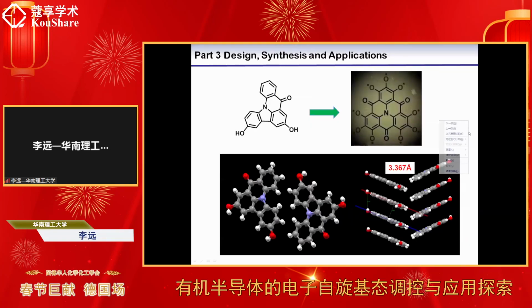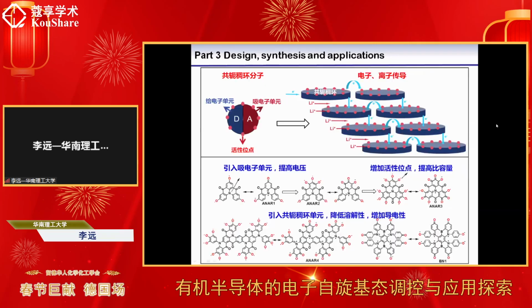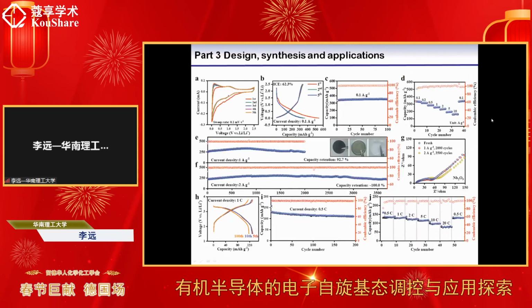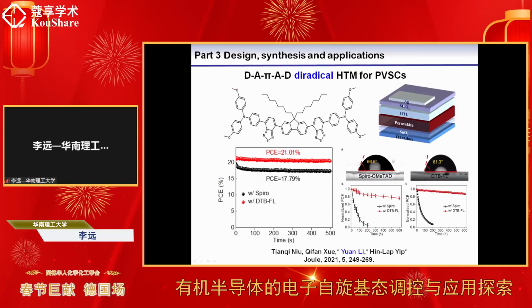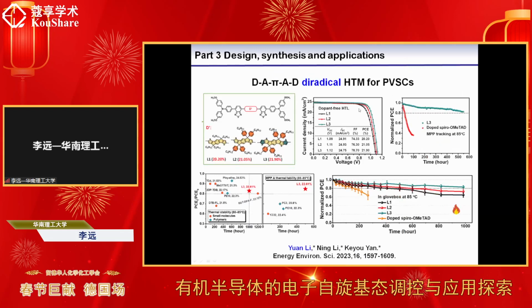And these are our results, which have not been published. We showed that the polymers based on radicals showed very good performance as the cathode of lithium batteries. It's very stable and has very high capacity. Also, we show some application of the diradical in perovskite solar cells, for this kind of DA-pi-AD diradical. It has a very weak diradical character, but this diradical character promoted the hole transport of these materials in the perovskite solar cell devices, and showed very high performance with non-doped hole transport materials, and very much enhanced stability of the devices.